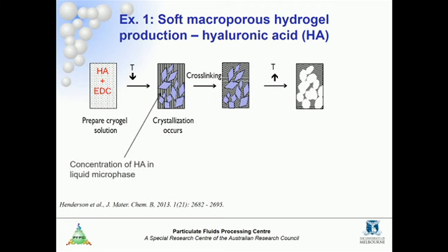And because we've only used water to make the pores, we don't have toxic components to remove. So we can get very high porosity, about 90% pores, so only 10% or so polymer, and very well interconnected pores. So there are pathways then for cells to move through. And we can tune the properties, and they're low toxicity because we're not using toxic components. So this picture shows you a very soft gel through to a stiffer gel. We can control the properties very nicely.